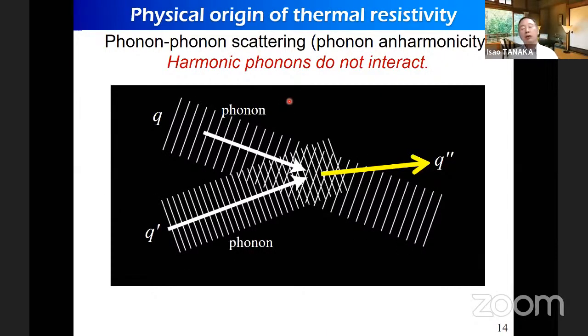We're interested in thermal conductivity or thermal resistivity, and the physical origin of thermal resistivity is phonon scattering, or phonon anharmonicity. You know that harmonic phonons do not interact. So if the crystal were composed only of harmonic phonons, you could expect zero thermal resistivity, which means infinitely high thermal conductivity. But in a realistic material at finite temperature, it does not happen. Phonons always have some sort of scattering, so by computing phonon scattering, we can compute thermal conductivity.